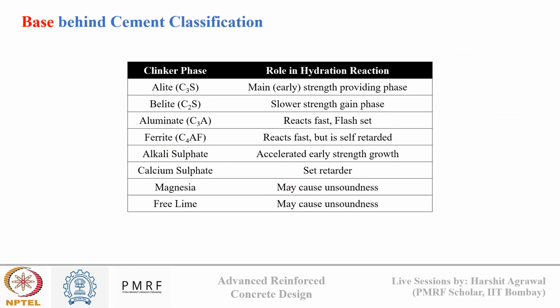For all these classifications of cement, the base is the composition of cement. By varying the chemical composition, we are varying the reaction kinetics of the cement. This variation in chemical composition, as we said, depends upon the proportioning of the raw meal and its quality, which makes the variation in the oxide composition. Now let's look at the role of the different compounds present in cement in hydration. We know alite is the main strength providing phase, the early strength providing phase, because in the hydration of C3S it produces CSH and CH.